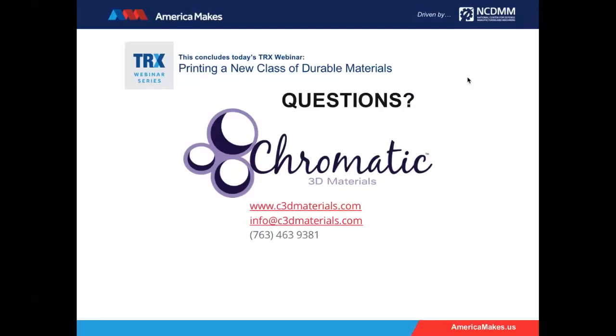Okay, thank you for that. And then if you wouldn't mind just touching on what about the surface finishing techniques and the resolution with your materials? Sure. So today, when you look at those flip-flops that I showed, that's printed with about a 0.2 millimeter nozzle. And I think one of the surprising attributes is that some of the surfaces are very glassy and shiny, even though it's printed with a relatively low resolution. Now, you can certainly go to higher resolution, and there are printers on the market that can do 2-component printing that go to as low as 20 microns at the nozzle tip.